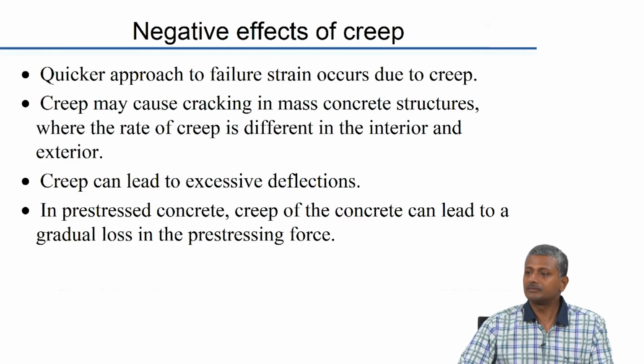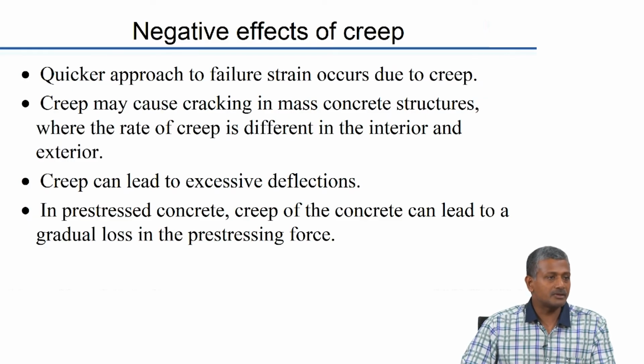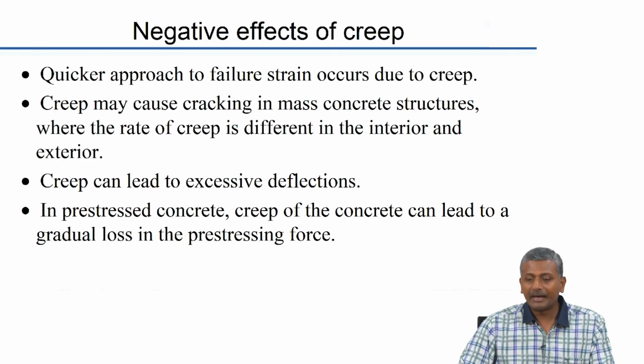Now, obviously, a quicker approach to failure strain occurs when there is creep. Mass concrete structures, when there is difference in strains in the interior and exterior, can get cracking because of that, and excessive deflections can happen because of creep, which we saw from that example of the arch bridge, which was shown in the first slide.